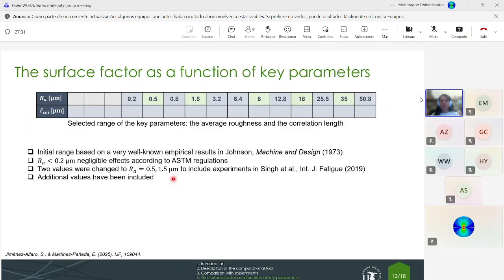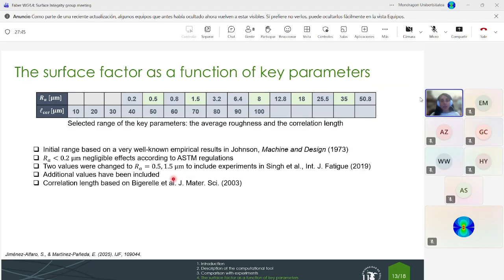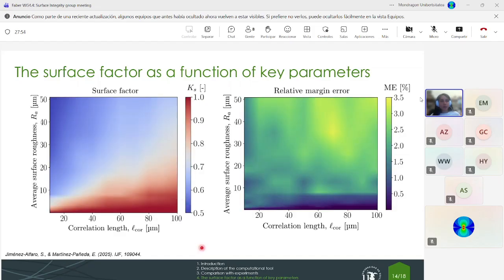And then we have included different additional values, just to have a more accurate analysis and to really get good evolutions for the key parameters. And for the correlation length, we have selected, as I've said before, a range that was found in the literature that was suitable. So now we have built this kind of operational maps where you can see that we show the surface factor as a function of the average surface roughness and also the correlation length.